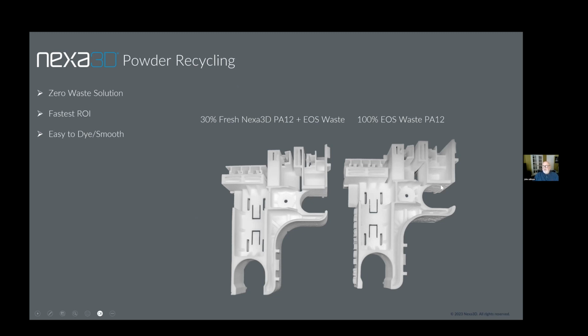We've been able to say, hey, look, this powder is pretty damaged. So what we need to do to bring it back to life is add a little bit of fresh powder to it, adjust the print parameters slightly, taking into account that mix. And now we can recycle the powder and it's perfectly acceptable. So a mix of 30% fresh with this dead powder from EOS or 3D Systems will clean up the elephant skin and sidewall to a degree to make the parts acceptable for use.